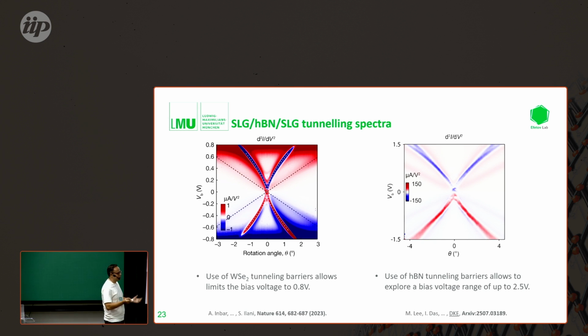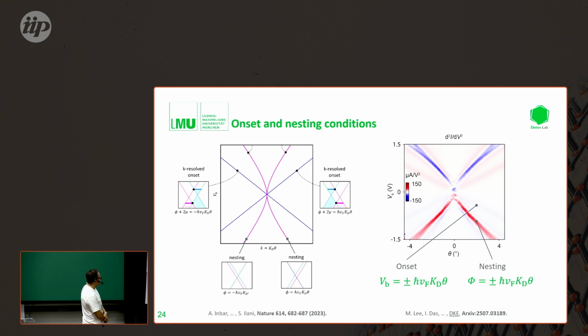This is related to just the area of the interface, so this is in every device. In the other conditions, again, the linear condition is the onset, and then there is a nesting condition, and this will become important in the last 5 minutes of the talk. The nesting condition is when the top and bottom layer band structures run in parallel to one another, where you get an extended k-space region where tunneling is allowed, and you have a lot of tunneling transitions.